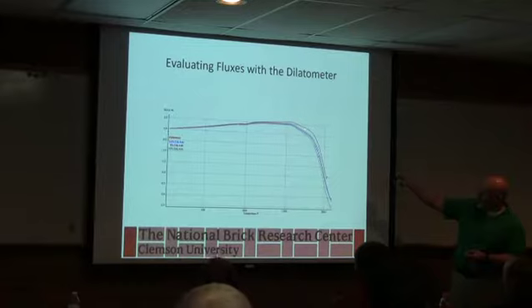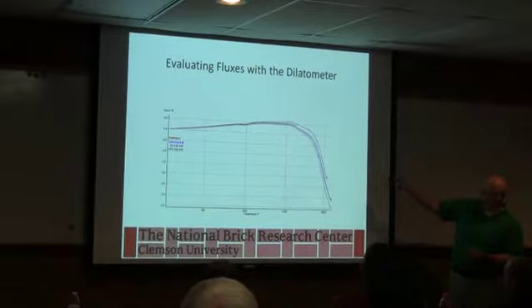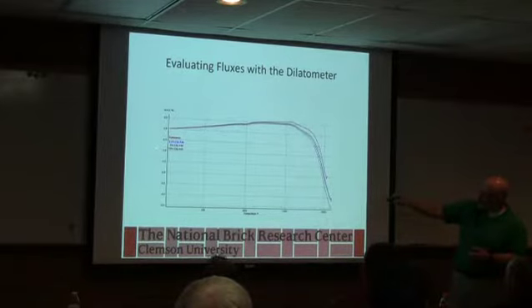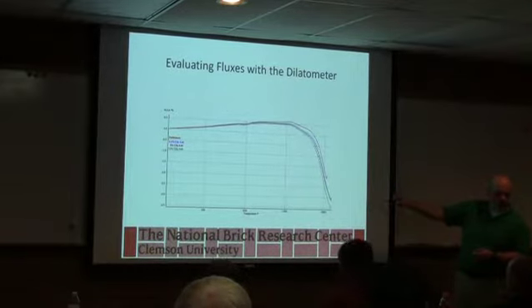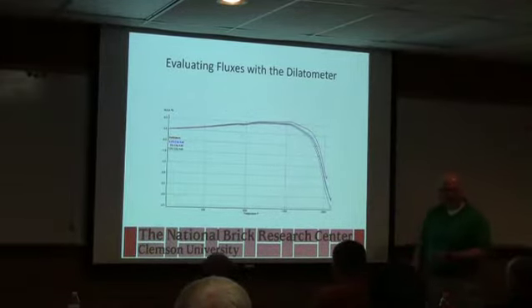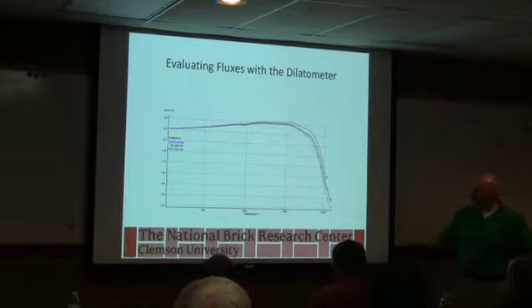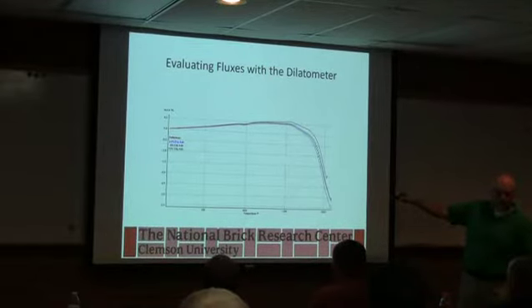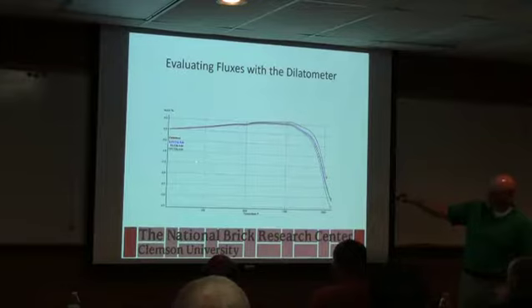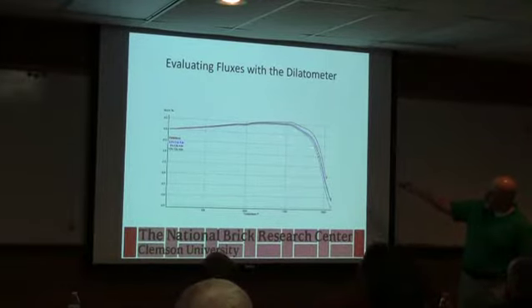Then you get out here and that clay relic we talked about, after we decomposed it, starts to make something called mullite. Okay, you typically see that in this range. And then we have the glass formation. So what we've done is we've taken, this is basically calcined sewage sludge that was, I can't remember what city was trying to get rid of it, but it's got a lot of potassium in it. So it's actually, if somebody will give it to you, a good flux. And we were trying to see how much it would lower firing temperature.